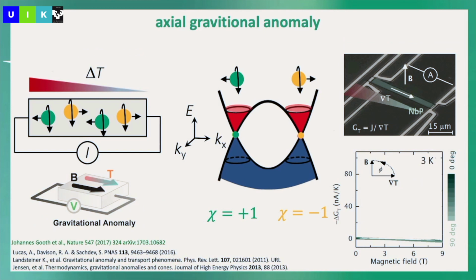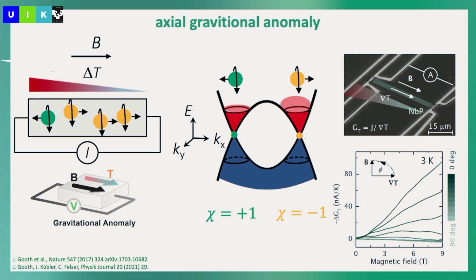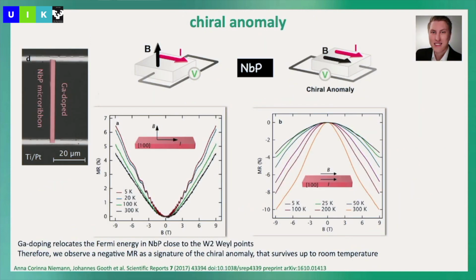But you can also do the same experiment by applying a temperature gradient, as I said, and it had more or less the same effect on the properties, which is in some sense logical, because the thermoelectric transport is related to the electric transport via the Wiedemann-Franz law. So we think this is a real measurement and no current jetting, because it fulfills the Wiedemann-Franz law. And this, as I said, was done with these nanoribbons, because here you also see nicely again the quantum oscillation, and so we could really see in this material that we had the Fermi energy at the W2 points.